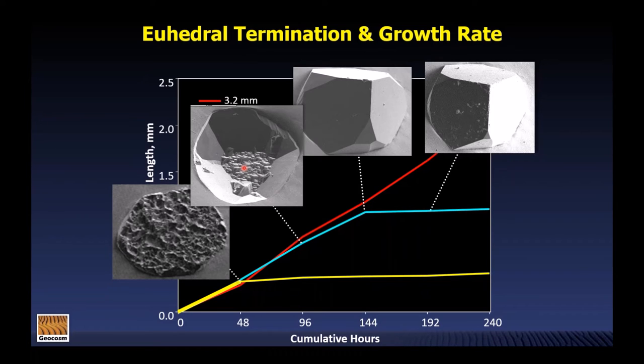Well, this surface, which is perpendicular to the C crystallographic axis, in fact does not correspond to a euhedral quartz face. And so what's happening here is when we look at the atomic structure on the edge of the crystal, we have a very high density of unsatisfied atomic bonds in this particular orientation. Each one of those bonds wants desperately to satisfy its charge imbalance. So anytime a dissolved silica molecule happens to be floating around, it wants to grab that dissolved silica molecule to satisfy its charge, and that grows a crystal rapidly.